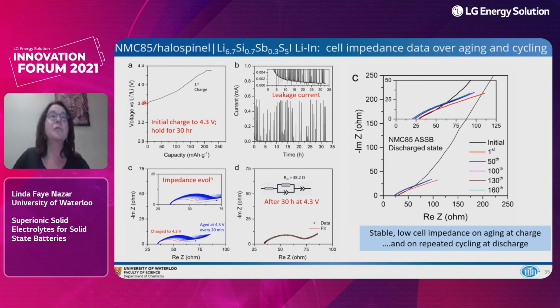So we take the cells, we charge them up to 4.3 volts, and then we hold them for 30 hours, which my graduate student, Laidong Zhou, who's done this work, he calls this aging. And so we monitor the leakage current until it basically dies off to zero, and we monitor the impedance every 20 minutes. And you can see that on this 4.3 volt hold for 30 hours, the impedance changes very little. And after 30 hours, we get a charge transfer resistance, which is very low, very modest, of about 38 ohms. And if we take the cell and we keep returning it to its discharge state, as we take it up to 4.3 volts, and then look at the impedance when we return it back to discharge over 160 cycles, there is effectively no change in impedance.